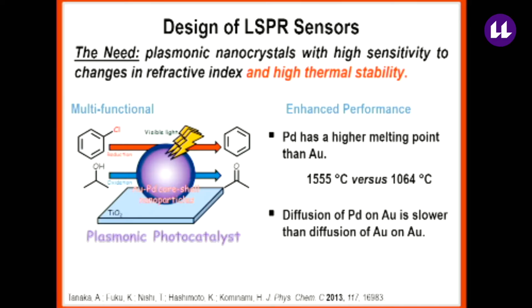in addition to considering the design of LSPR sensors, one of the other things that we were particularly interested in was thinking about how our nanocrystals may provide greater thermal stability. Some of the challenges in using all gold platforms is that once you shine light on these gold platforms, you're dumping a lot of energy into the systems. The gold atoms are quite mobile. They'll restructure and you'll get a shift in the LSPR position. And so then you can't reuse those nanocrystals in future applications because you're going to have poor overlap with your laser or whatever light source you were using.